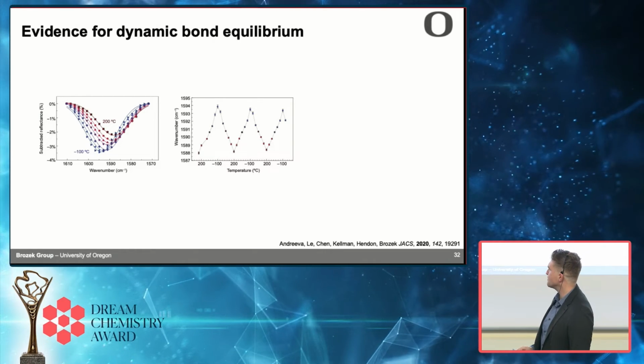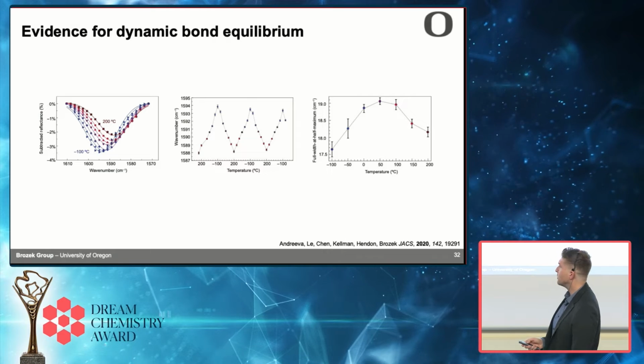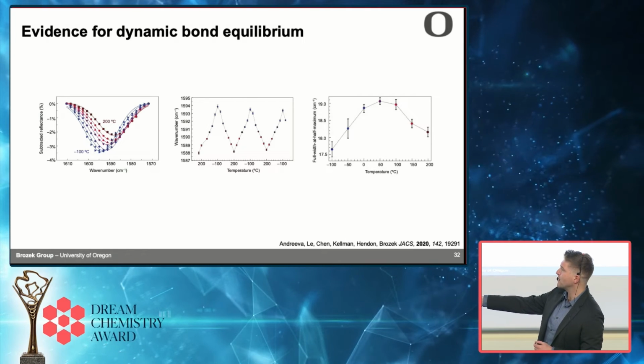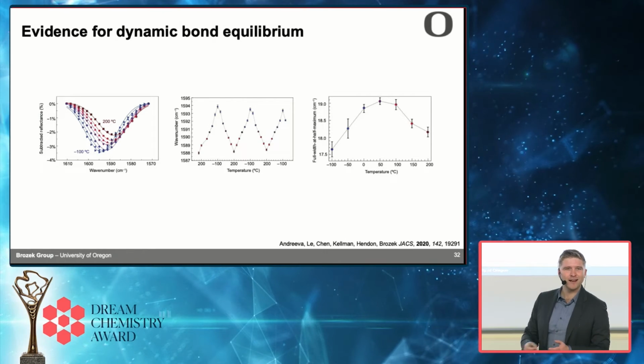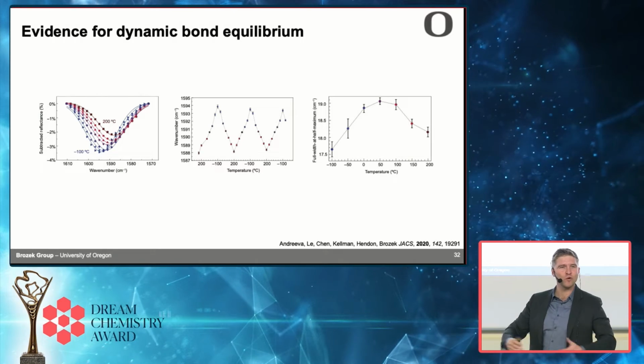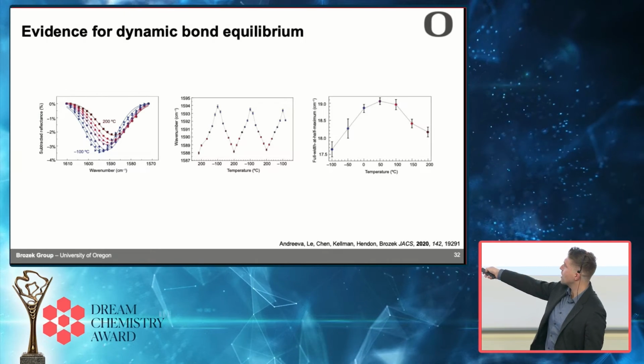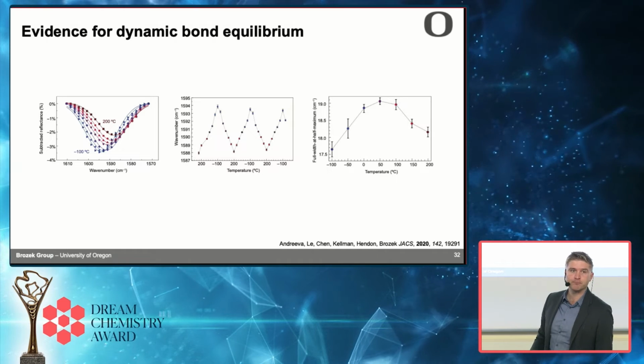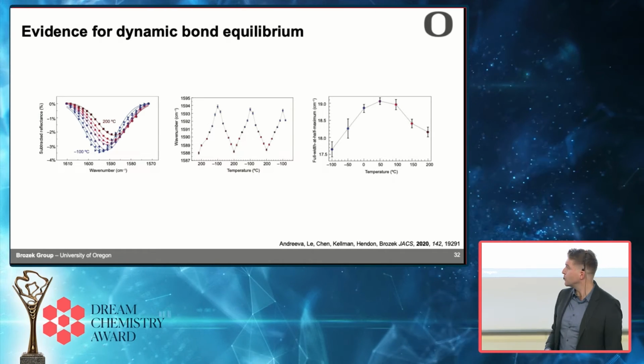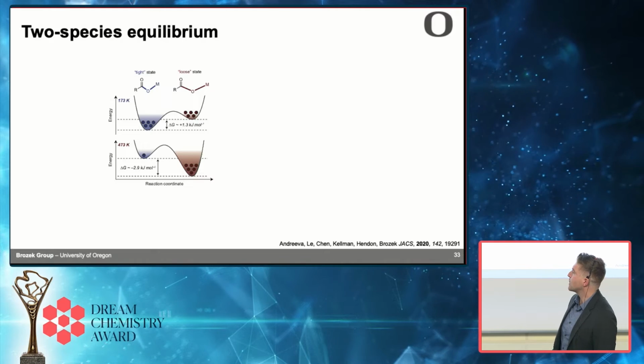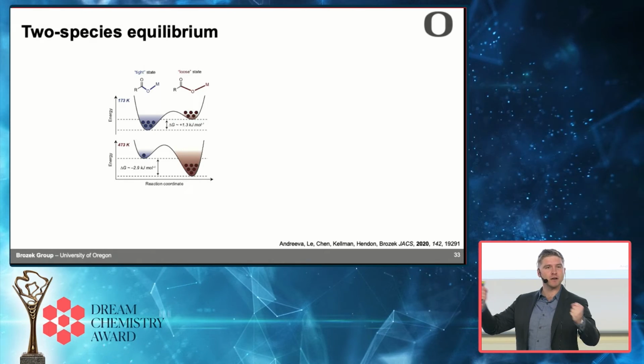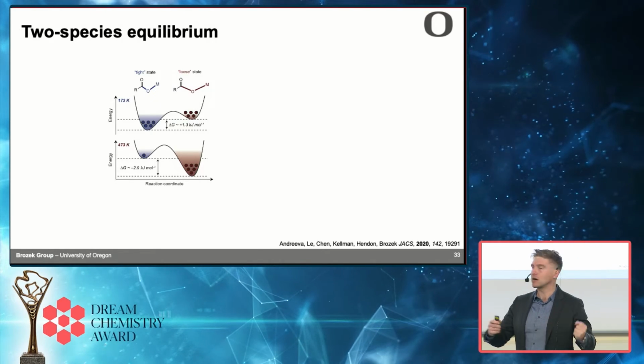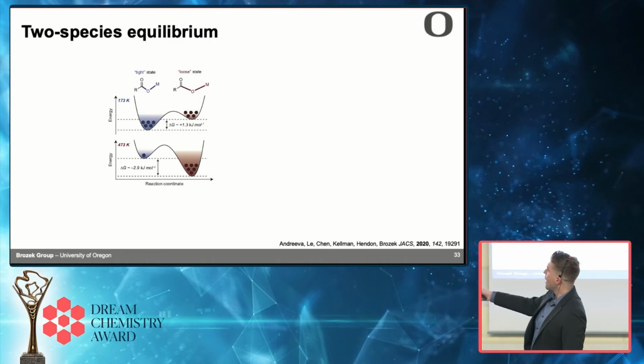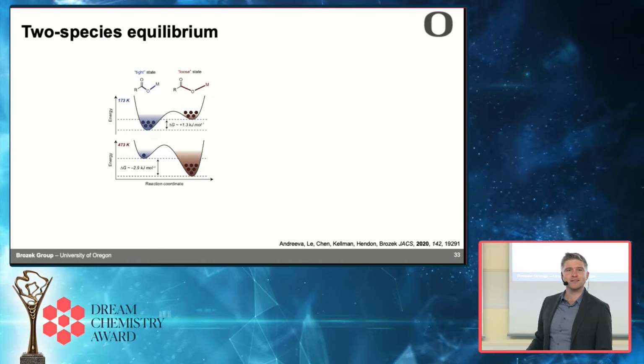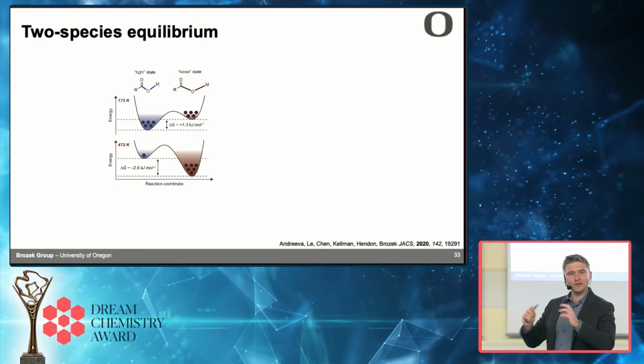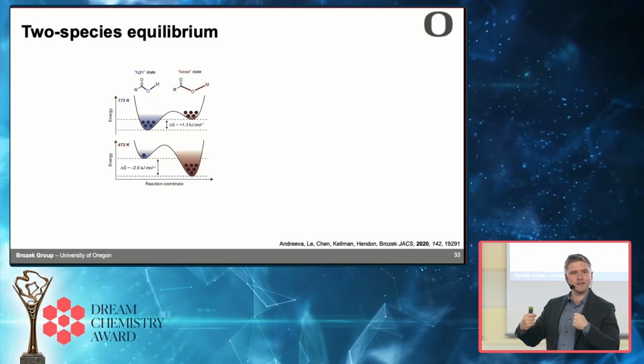But perhaps the most useful thing that we saw here was when you plot the width of the peak, the full width at half max. I thought that as you heated it up, it would just get broader and broader, more disorder. But instead, it was actually broadest at an intermediate temperature. It turns out that was cluing us into something important: we're looking at two different species in equilibrium with each other, sort of like that bound and unbound. We figured that you had a collection of metal carboxylate bonds. They're a little different from each other, but they're all relatively tightly bound.